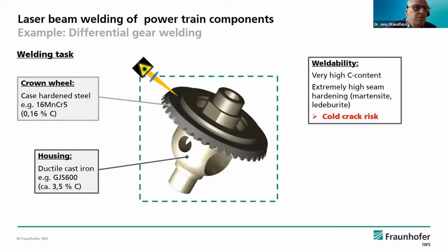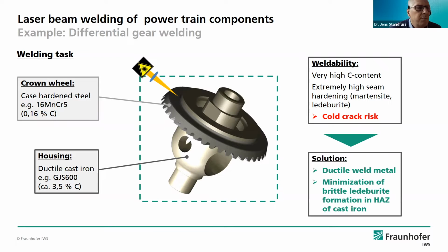with the high carbon content of both materials. And so we have extremely high hardening inside the seam, and we have a risk for cold cracks. So we must have some technology proven with respect to the material and to the parts themselves. And the solution, from the welding side, is that if we have some hard to weld materials and some high strength materials, if the weld is ductile, we have a chance to weld it without cracks. And it needs, in more detail, to minimize the so-called ledeburite formation in the heat affected zone of the cast iron, and so we get some perfect welds.